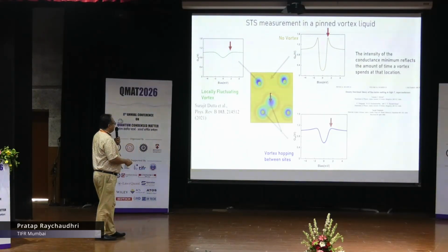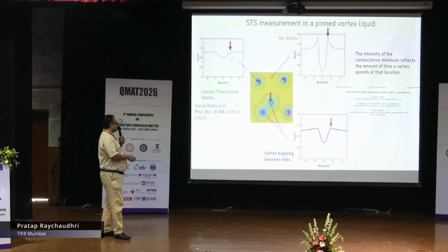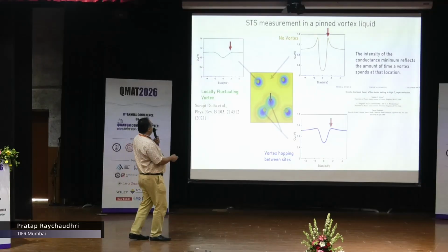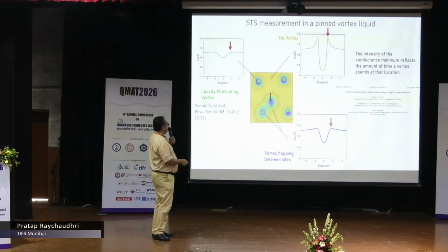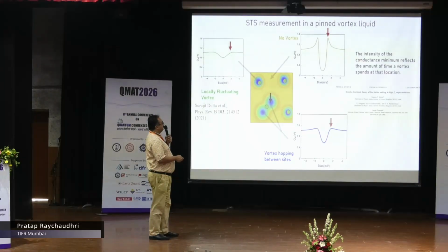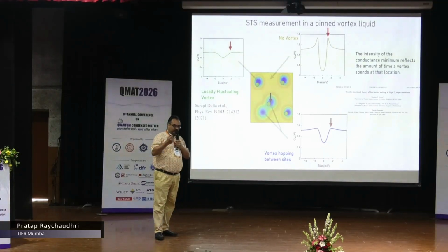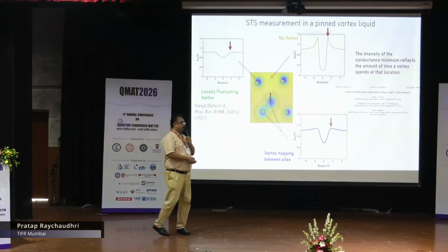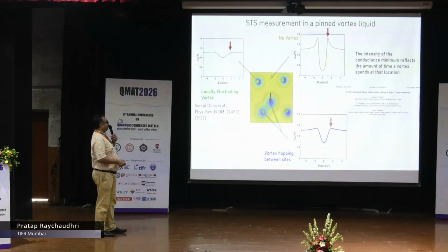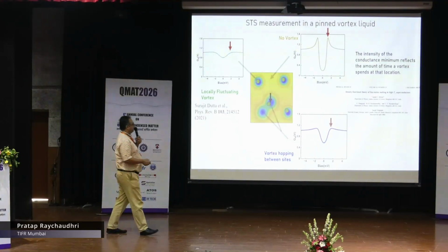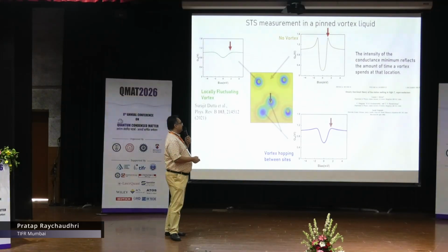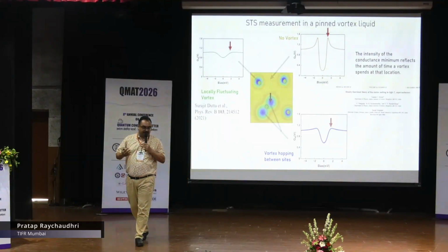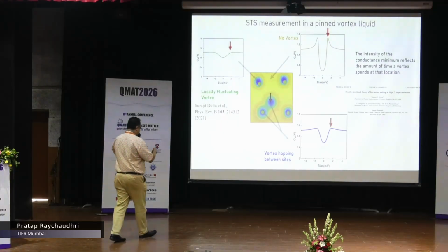On the other hand, if I bring my tip here, where the vortex is jumping between these two sides, the tip will see the vortex core only 50% of the time, which means that you will have a spectrum which is in between these two. And this means that the intensity of the minima in the conductance map reflects the amount of time the vortex spends at a particular location. In other words, it's like the probability density. These ideas came mainly from this paper, which is a density functional theory of flux line lattice melting. And this is the application of the famous density functional theory of melting by Yussouff and Ramakrishnan applied to vortices.